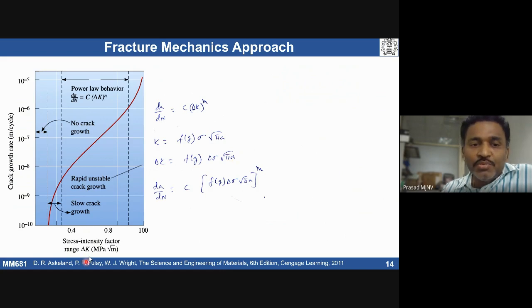So with respect to stress intensity, because under cyclic loading condition, I'm giving delta sigma or sigma A. Sigma A is nothing but delta sigma by 2. So in the cyclic loading conditions, we need to talk about stress intensity factor range, because we are changing the stress minimum and maximum, and monitor how the crack growth is taking place for different stress intensity factors.